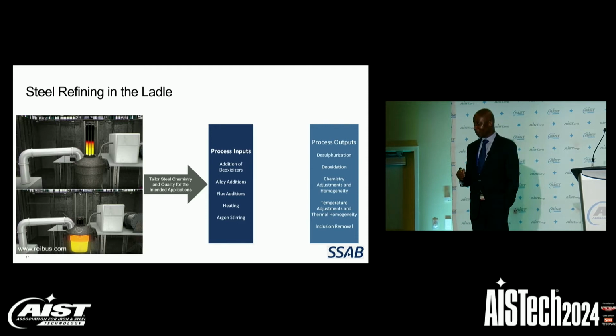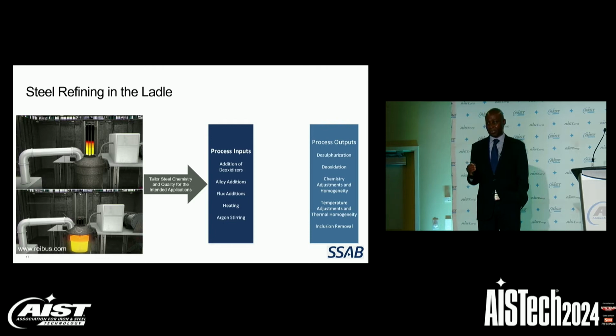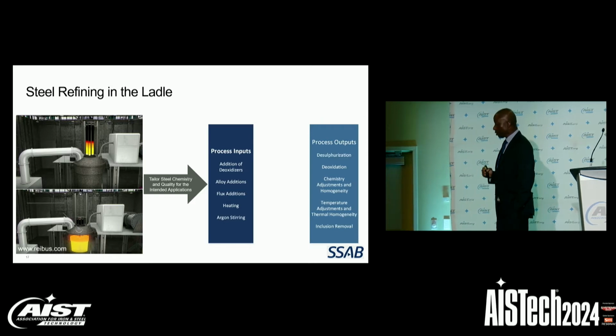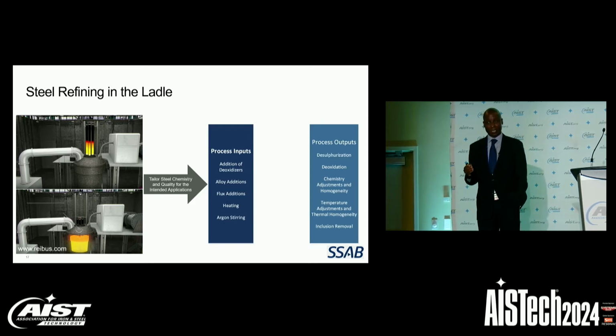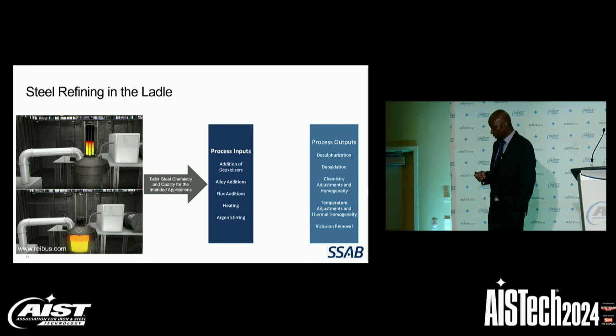They have to provide adequate heating to the bath to make sure that the ladle is sent to the caster at the required temperature. They have to ensure good argon stirring in the ladle to ensure that we have chemical and thermal homogeneity. And they also have to ensure that in that process, they enhance inclusion removal before the ladle is sent to the caster.